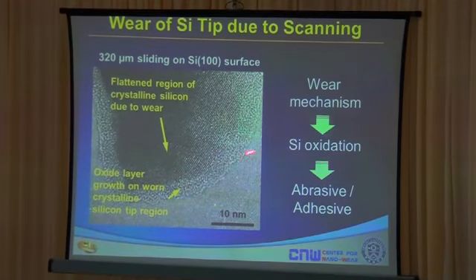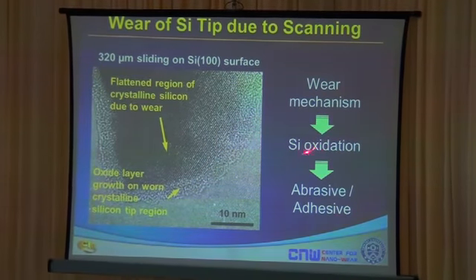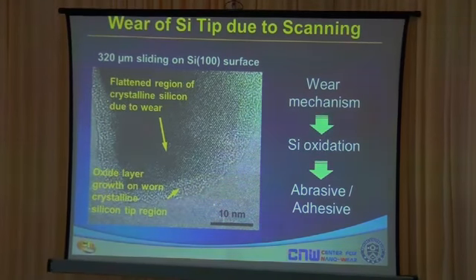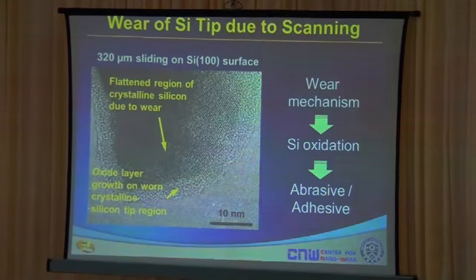What we did here was we performed 320 micrometers of sliding on silicon surface, and what we find is that the region at which there was contact was flattened due to wear. And by noting the shape of the tip before and after the wear test, we are able to quantify the wear amount. And also, furthermore, we're able to suggest the mechanism of wear. And this is the mechanism we suggest, is that the silicon tip becomes oxidized, and this oxidized layer, because of abrasive adhesive action against the specimen surface, will eventually wear out.